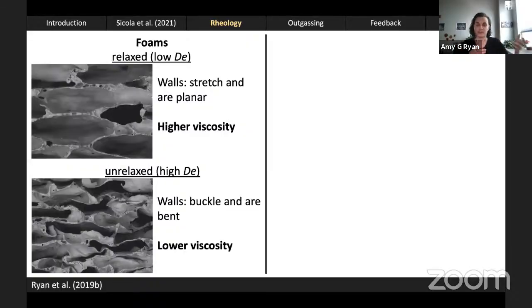So a material deforming at low Deborah number, where the melt is nice and relaxed, as it's being compressed, the bubble walls have the capacity to respond relatively quickly to that deformation. So what they end up doing is that they'll stretch, but overall they'll maintain their most stable configuration, which is to be near planar or very, very slightly curvilinear. And as deformation continues, they're able to maintain that planar shape for the most part. Maybe we get 1 or 2 bent ones, but you can see overall, everything here is pretty flat. And that stable configuration of bubble walls actually makes the composite, the foam, quite stiff. And that's evidenced by the high viscosity that we actually measure.